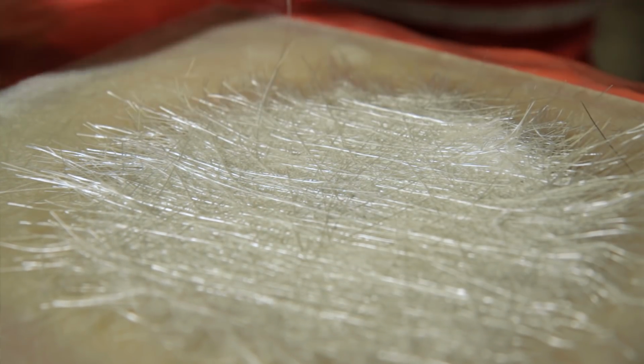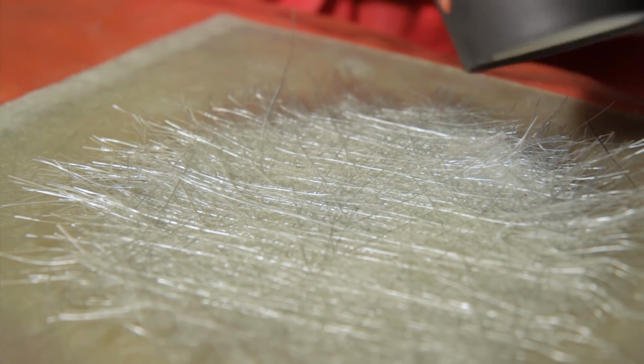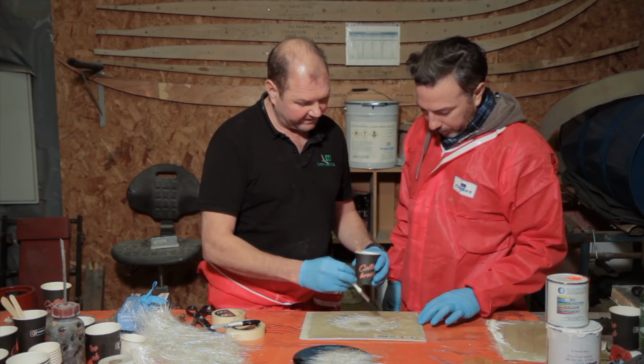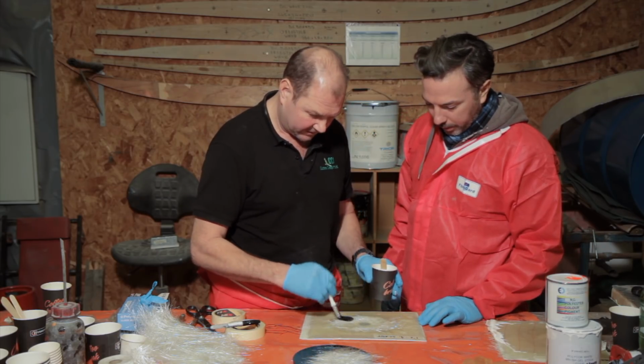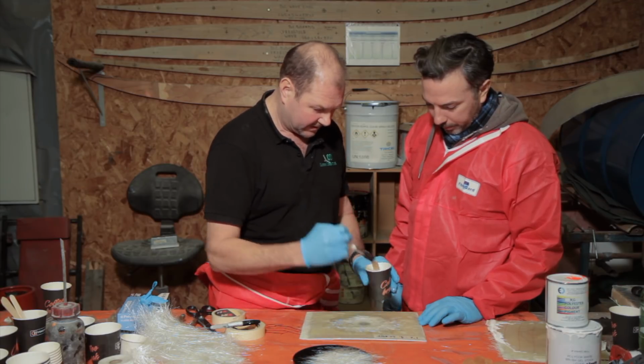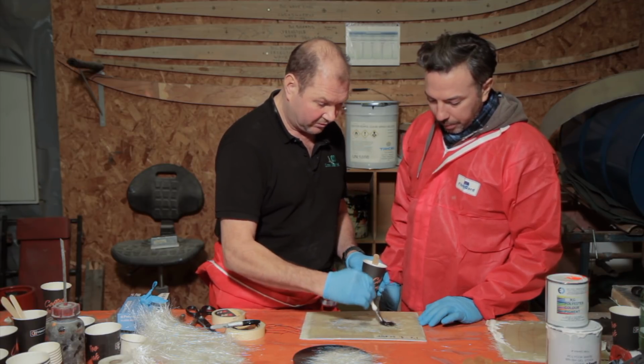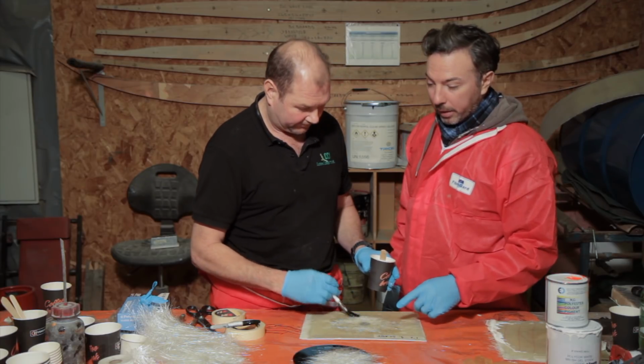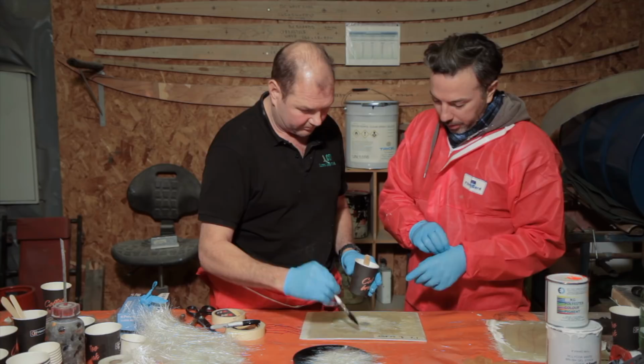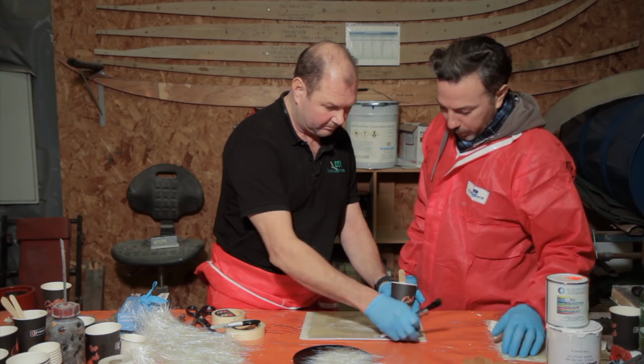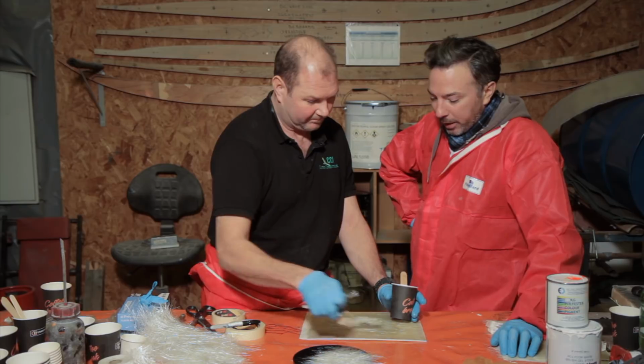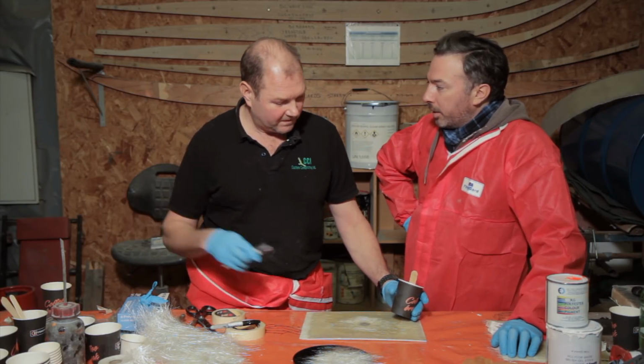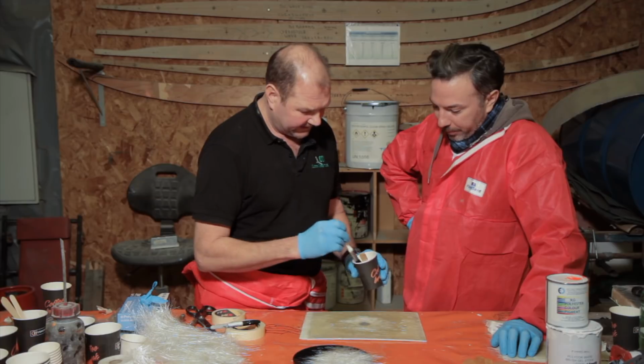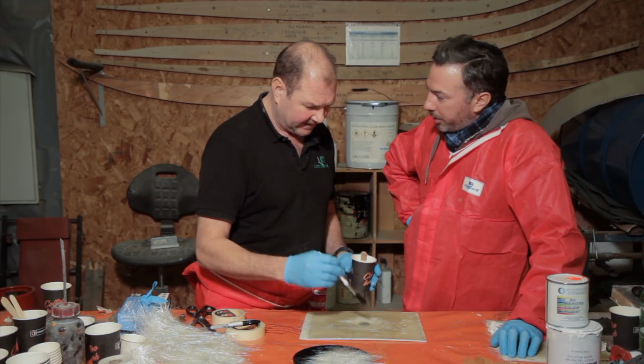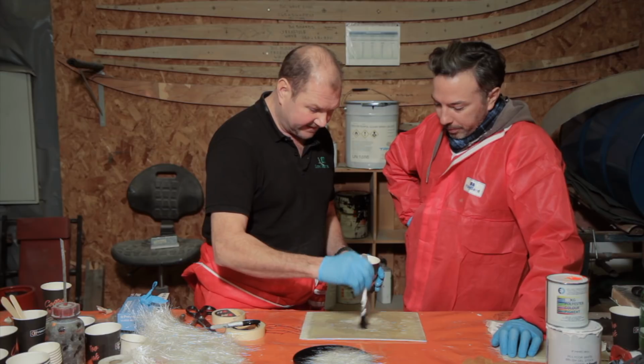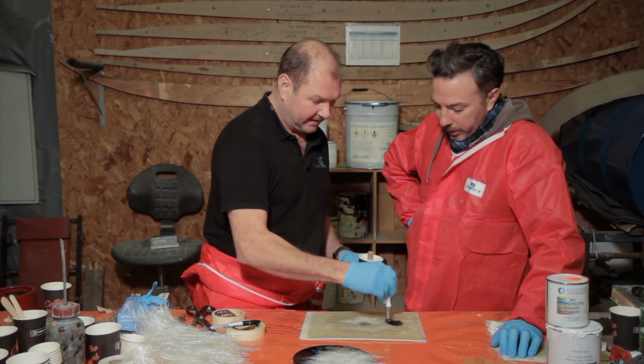Right, so now we've got the first layer on. We're just going to wet this out. Now, resin will bleed through from the underneath where we painted it. And basically, use one layer at a time. Now, I was in the bilges of a catamaran doing this, using matting like this, doing a structural repair, and when it was inspected afterwards by the skipper, he said it wasn't bad, but then he looked again and said there was a lot of air bubbles in it. How do I avoid that? Air bubbles. Maybe did I mix it too vigorously or something like that? Possibly. Stippling is the standard method. That just gets into all the fibres.